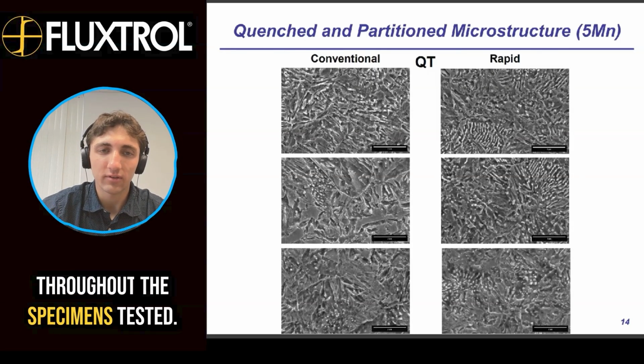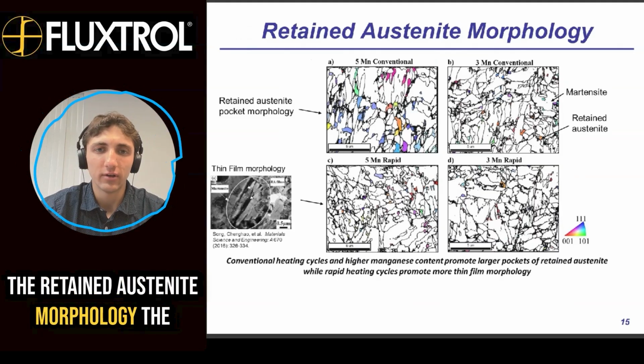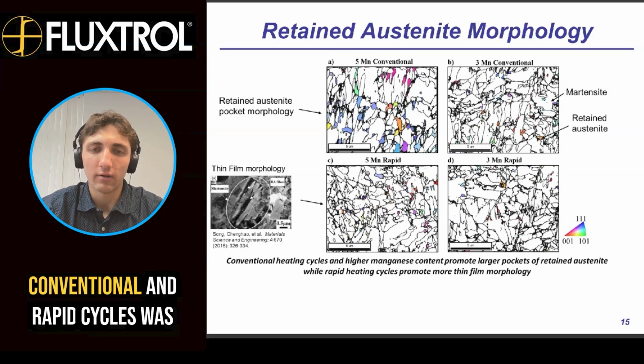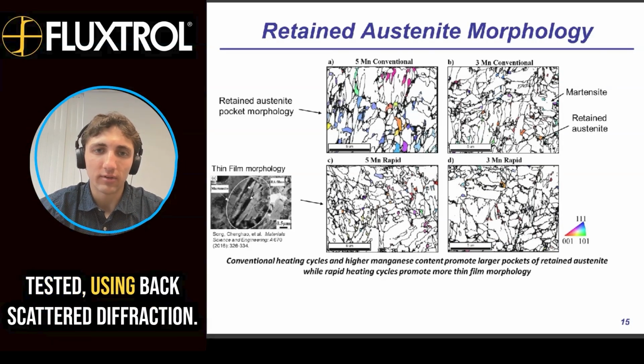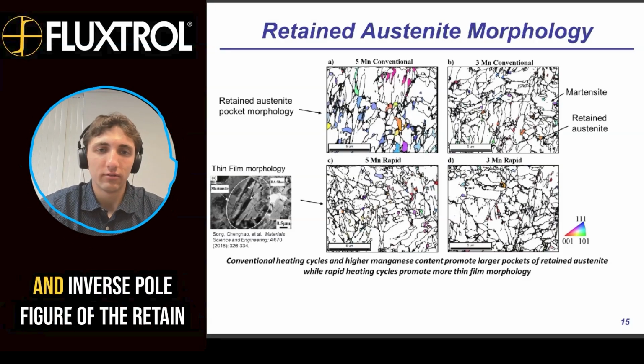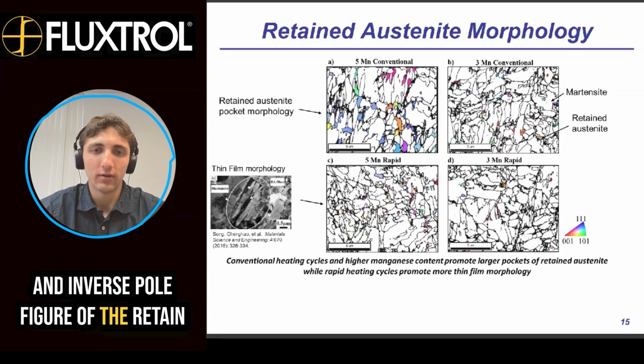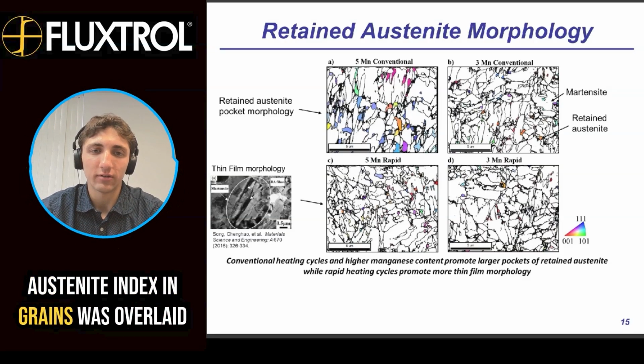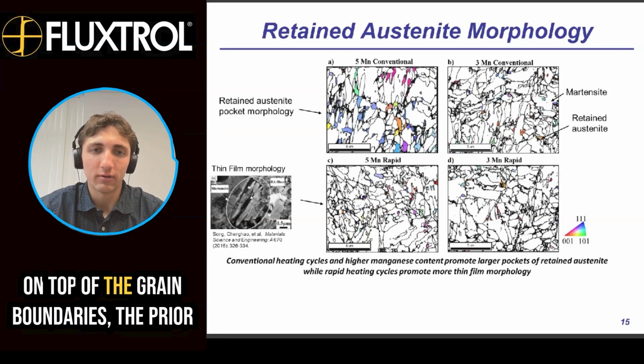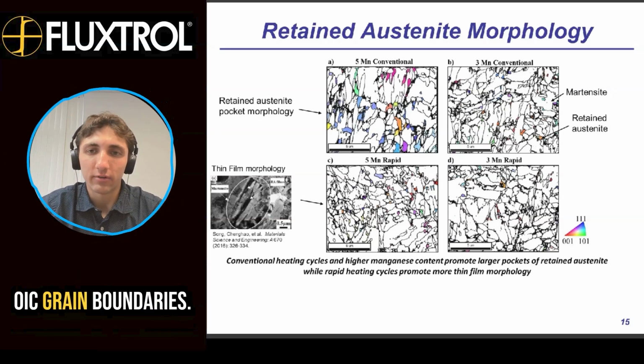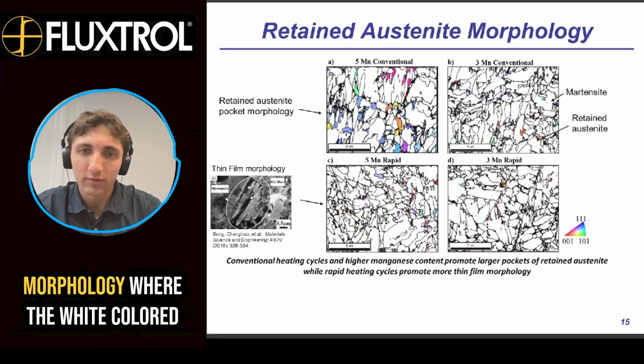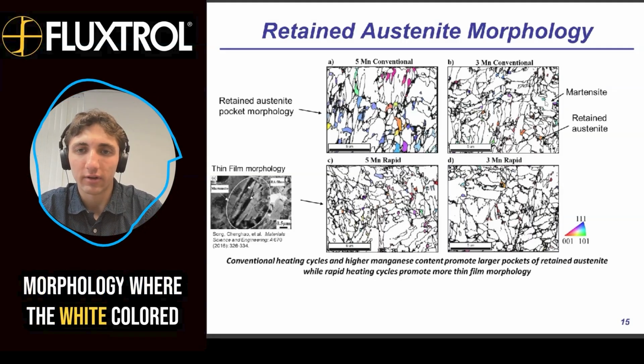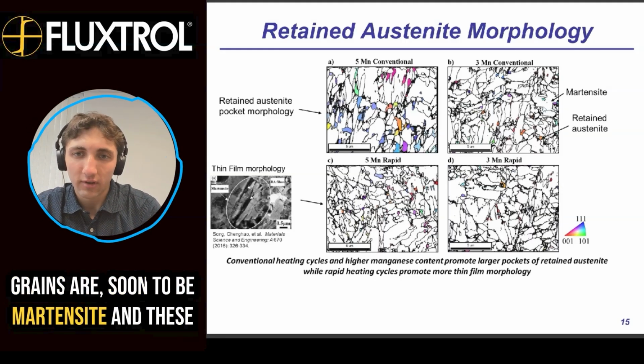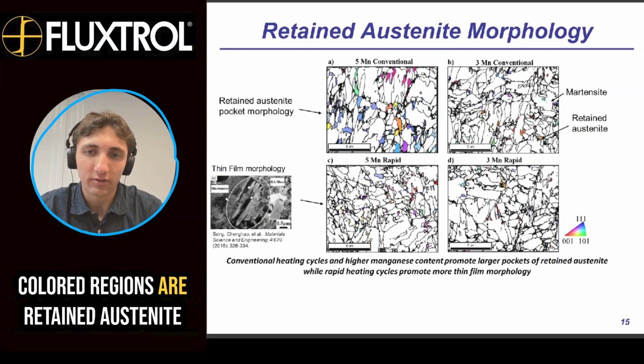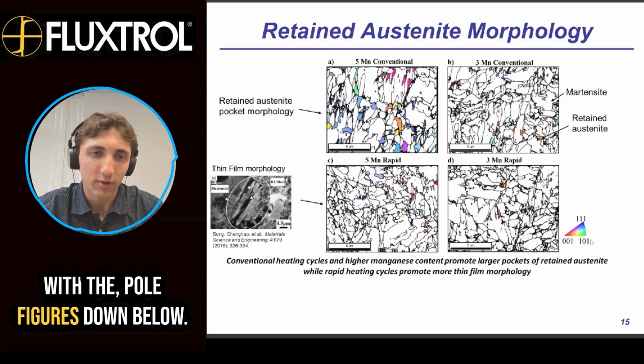The retained austenite morphology, in the conventional and rapid cycles, was tested using backscatter diffraction, and an inverse pole figure of the retained austenite indexing grains was overlaid on top of the grain boundaries, the prior austenite grain boundaries, in order to show the retained austenite morphology, where the white colored grains are assumed to be martensite, and these colored regions are retained austenite with the pole figures down below.